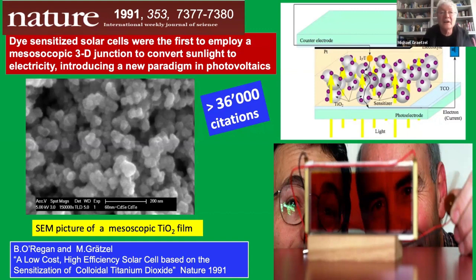Yeah, at the end, these studies culminated in the paper we published together with Brian O'Regan in 1991, and that reported on these cells which, as I said, consisted of these nanoparticle arrays covered with a molecular sensitizer. And then it's very simple. You just need a collector, conducting glass at the front and at the back side. And this is how the cell can be made. And you see one of those devices here. It looks like a colored glass plate, but it's a photovoltaic cell. And in ambient light, it turns this fan.